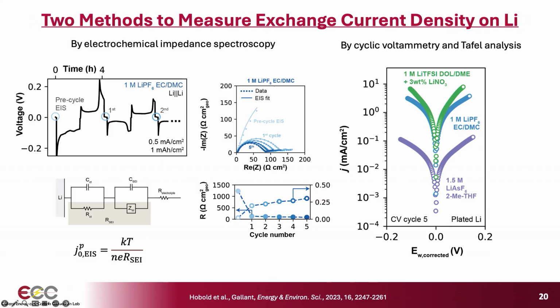I won't go into all of the details, but in both cases, we were cycling the cell to expose a fresh lithium surface, then we allow that lithium surface to react, and then we probe the exchange of the SEI that forms. In the first case, we do galvanostatic cycling with intermittent impedance spectroscopy. We can use an equivalent circuit model to fit the spectra, and then we pull out a measure of J naught. And in the second case, we do cyclic voltammetry with Tafel analysis.